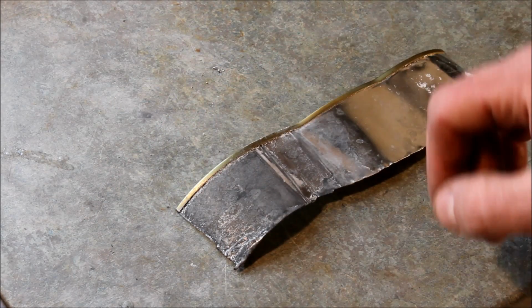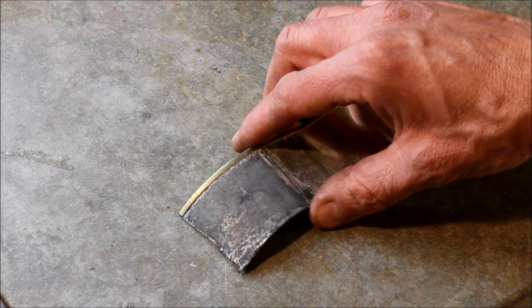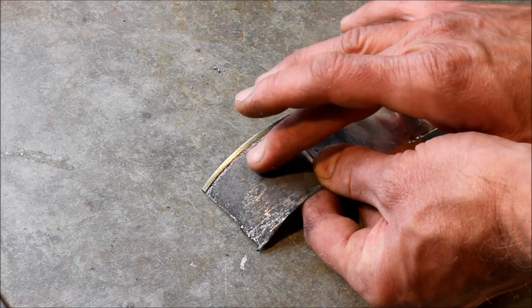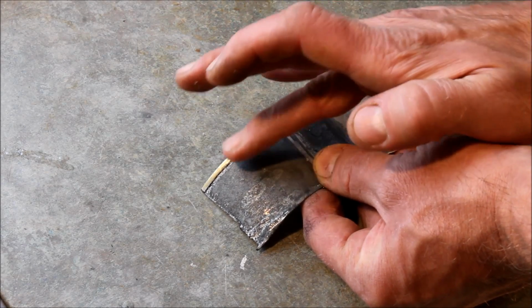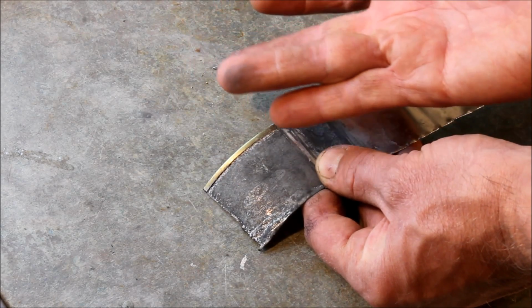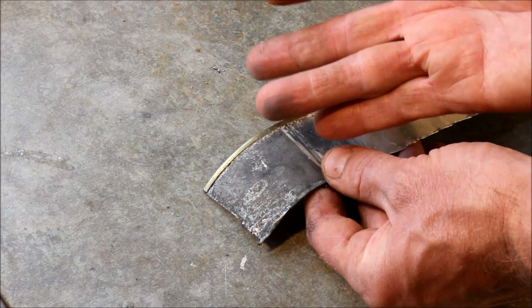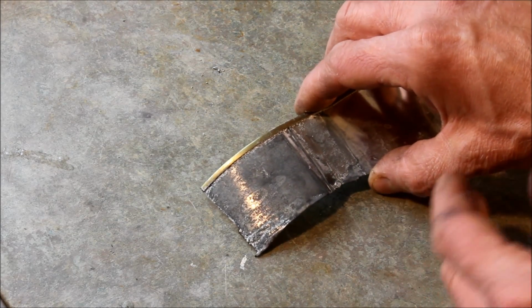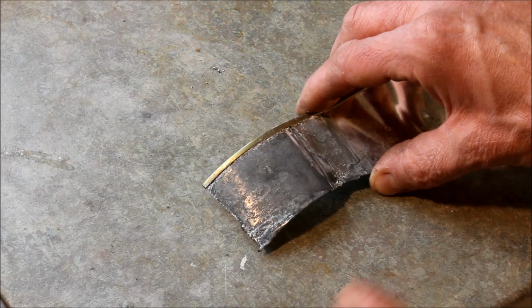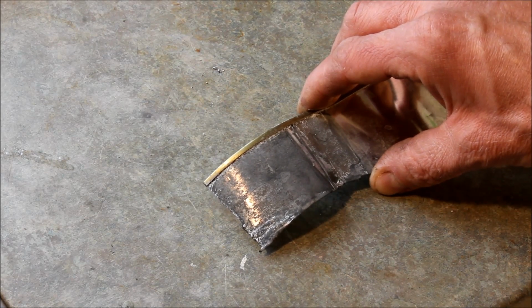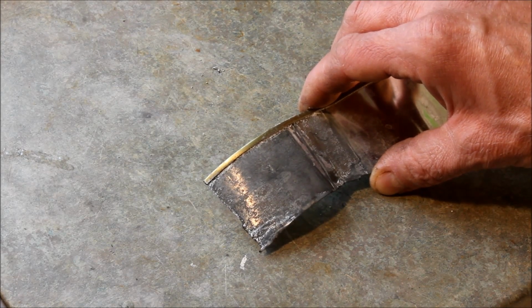Often the deposit is streaked, you can see the current lines running through the plate. And it's also often very rough, coarse to the touch, feels like a Brillo pad, and it's also often very soft. If you rub it, you see it just comes off on your fingers there. So that's burning, and that's just caused by too much current. If it's all over the part, you've just got too much current flowing through it. So check your surface area calculations and change the current.